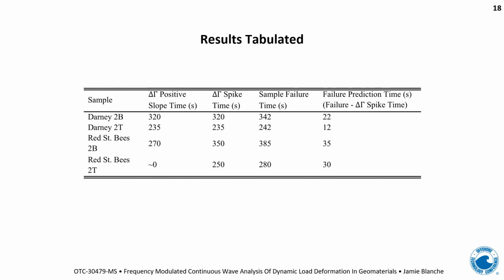So, with all the results collated and tabulated, we can see that there is a consistent trend that gives us a reflection coefficient spike time that occurs well in advance of the actual sample failure, which ranges between 12 seconds for the Darney top sample and 35 seconds for the Red St bottom sample. So that seems to be a fairly consistent range.